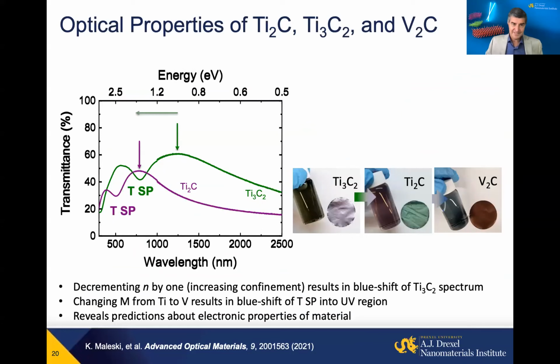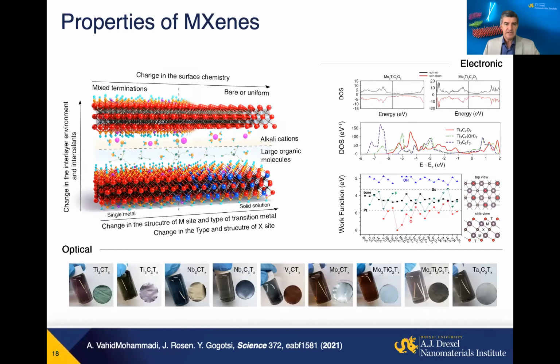Yes, but let me tell you here. First, I already mentioned very briefly that, say, Boris Yakobson predicted chemistry-dependent superconductivity in Mo2C, Nb2C. Dmitry Talapin at UChicago, and unfortunately, again, I did not include any figures on this, showed that Nb2C goes to a superconducting state at several Kelvin, but only with a certain termination. Actually, it was sulfur, selenium, tellurium, I believe. And if it's oxygen, it won't.